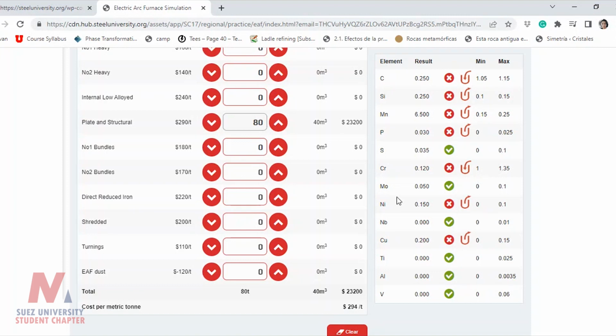That's the game. At the beginning of the simulator, you definitely have to choose the right kind of scrap, because if you add 80 tons of plate and structural, trust me, you will never reduce the nickel and the copper percent. So starting from this, you have to choose maybe internal low alloy, and then we use here 0. And as you see, we still have molybdenum and nickel.